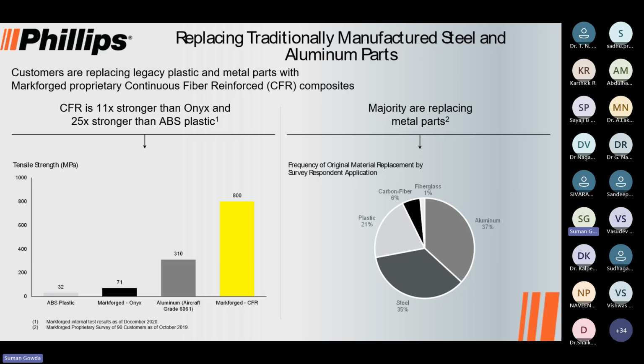Yes, we hardly utilize 100% of the fiber strength, but even if you are able to utilize 50% of the fiber strength when we deposit in the parts, we are still getting parts which are similar to or superior to the strength of an aluminum. We have got a lot of customers who have started their production even without a CNC machine. So they are printing all kinds of clamps, holding grippers, tools using a small FDM-based composite 3D printer, which can give them parts as strong as aluminum. We have got drone customers who are using around 10 to 20 of such printers as a farm so that they can directly print an end-use component of drones. So overall, we are talking about transition from a regular machined aluminum or a casted aluminum to 3D printed composite parts, which can give us the equivalent strength.